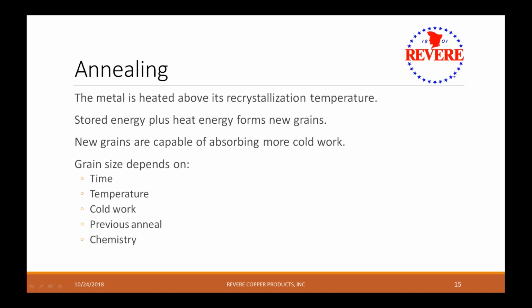So with annealing, the metal is heated above its recrystallization temperature. Stored energy plus heat energy forms new grains, so those grains grow again, and those new grains are capable of absorbing more cold work. So now you can roll it down further. So the grain size depends on time, temperature, the cold work done previous to the anneal, and if there was an anneal done previously, and also the chemistry, how pure it is, if your copper is 100% copper, or if there's impurities in it.